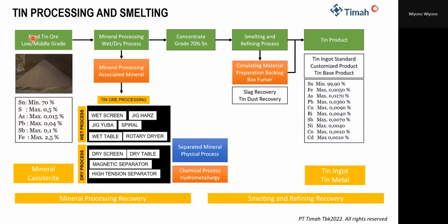Firstly, the feed tin ore before we do mineral processing. The input or the feed is low or middle grade, below 70%, as I said before. We must increase the grade of our tin concentrate to a minimum of 70%. This is our requirement for our tin concentrate.